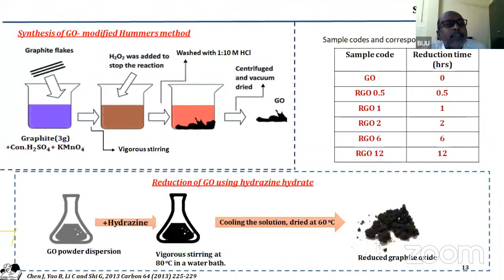We have followed the conventional modified Hummers' method for the synthesis of graphite oxide. Graphite oxide means you have graphite layers which are first oxidized and then exfoliated. That is the precursor material for the synthesis of reduced graphite oxide. It is a very common method where the details can be found in literature.